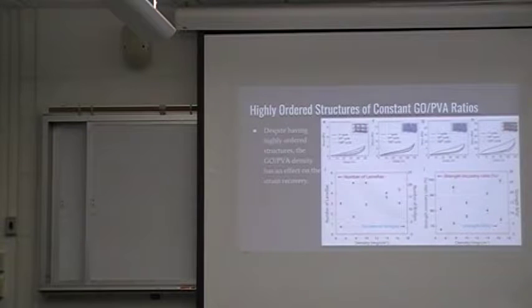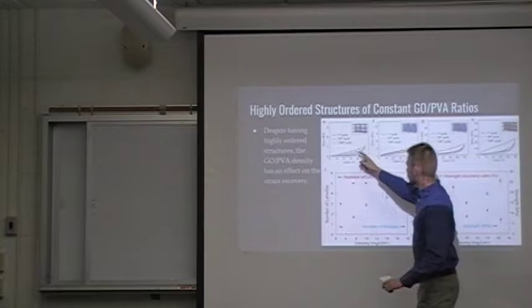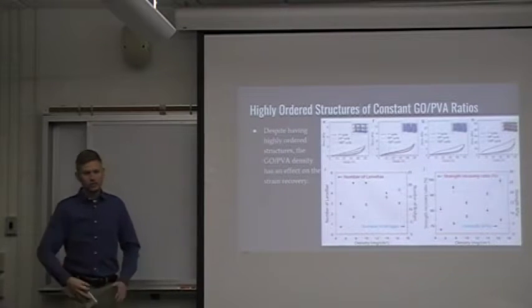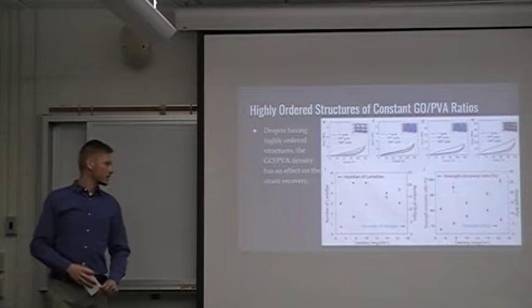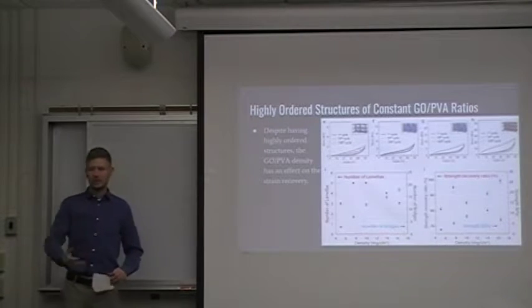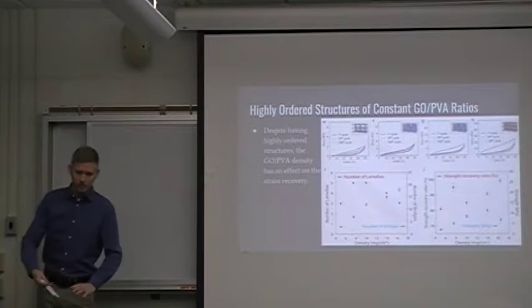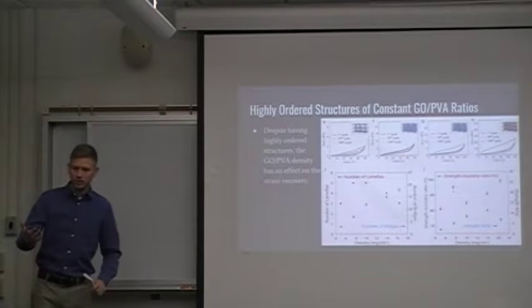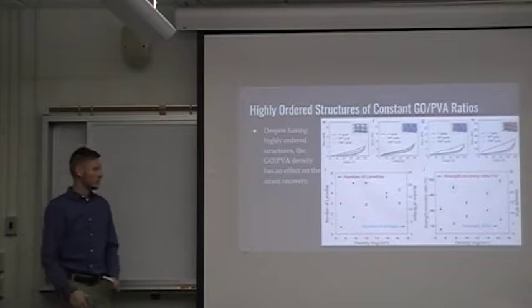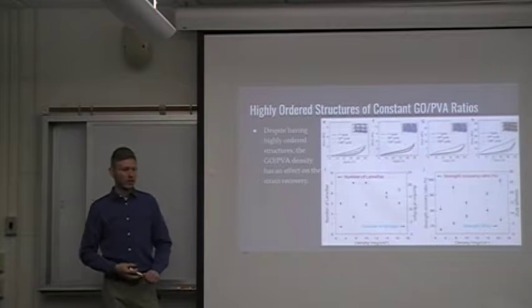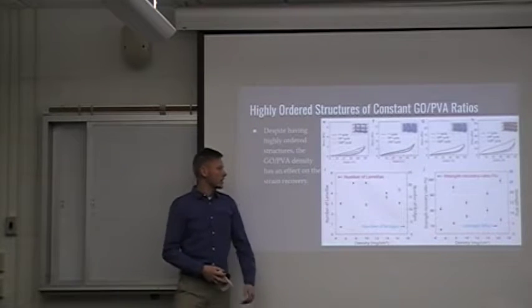And also, it is noteworthy to show that the scale changes on the y-axis. That is saying that naturally they are more dense as you add more GO PVA material. Thus, naturally, you can conclude that it is harder to squish, and it takes more force to squeeze more material. However, they do not always bounce back the more dense they are, as indicated in the graph.